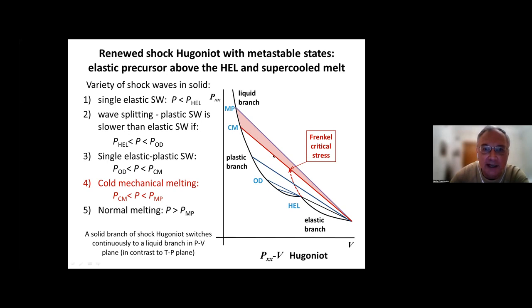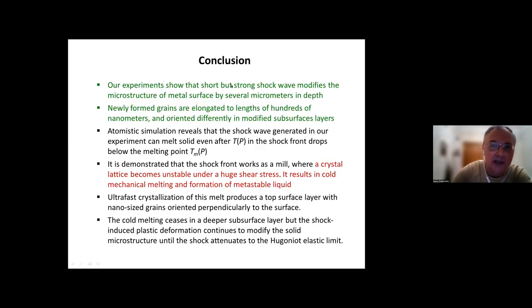And above this, in the red area, when the stress in the elastic zone, so it means ahead of the plastic deformation zone, exceeds the Frenkel critical stress, the cold melting begins; the red area indicates this regime. So, of course, with a very high increase of pressure, we reach the melting point and normal equilibrium melting, and the liquid branch starts after this point. So, in conclusion, I have to say that our experiment demonstrated that very strong shock waves, melting shock waves, really change the microstructure of metal by several micrometers in depth.